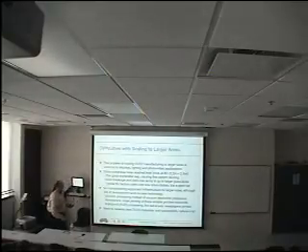Okay. Good. So here's one of the major problems right now that's specific to these kinds of solution processing and inkjet printing technologies. On this side, these are some solution processed large area emitters, and the scale here has actually been exaggerated so that you can see by eye what the differences are. Really, from brightest to dimmest, this is only going from like 100% to 90%. So this is really a 10% maximum variation in light intensity over this whole area here.